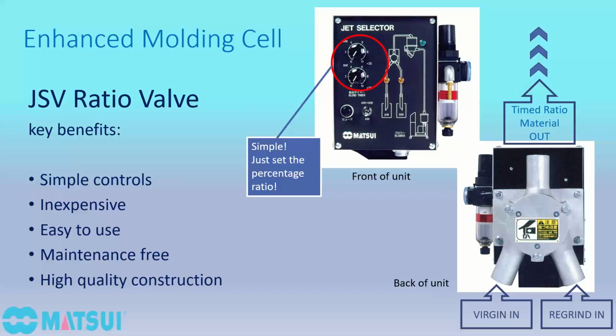You can ration it directly to the injection molding machine, the vacuum hopper that's on the injection molding machine. They're ideal to use in situations where you're producing less regrind than the maximum amount allowed. If your customer wants you to run 80% virgin, 20% regrind, or 70% virgin, 30% regrind, and that mix has to be exact each and every time, a rationing valve probably doesn't have the accuracy to do that, and you would at this point want to go to a volumetric or gravimetric blender. But for a small, compact, simple, inexpensive way to ration virgin regrind material, a rationing valve is a good choice.